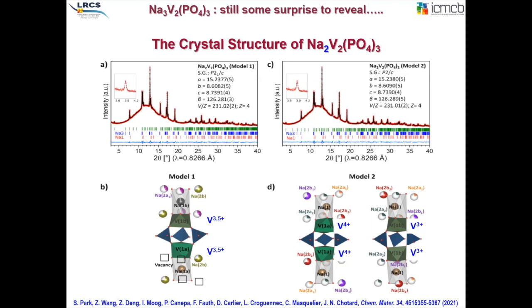This is pretty fascinating to see that in an apparently very flat voltage plateau, we indeed have a crystallized, well-defined phase just in the middle, between the Na3 and Na1 phases.